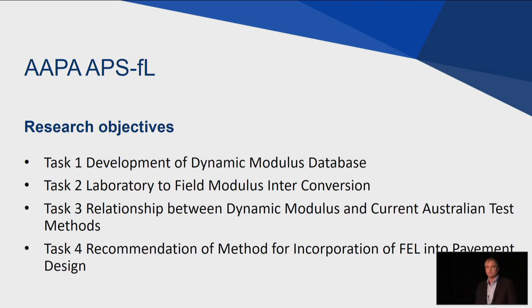These were the research objectives for that project, and I will say that with the benefit of hindsight, it was maybe unfortunate that it was so focused on dynamic modulus, the dynamic compressive modulus, because that's not very compatible with the Austroads pavement design method, which uses flexural modulus. So it was very heavily focused towards dynamic compressive modulus, developing a database for typical Australian mixes, coming up with a laboratory to field interconversion for that modulus, and then also determining the relationship between dynamic modulus and current Australian test methods, so that would have been the resilient modulus and the flexural modulus.